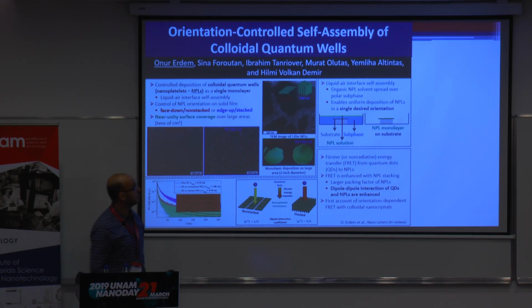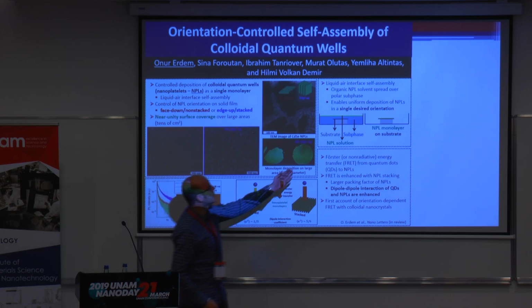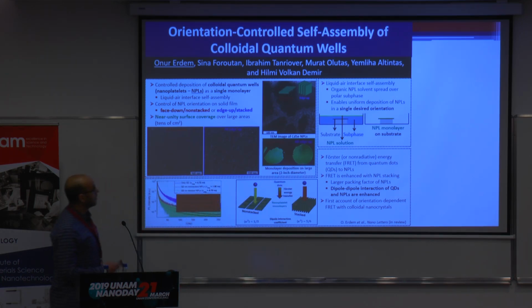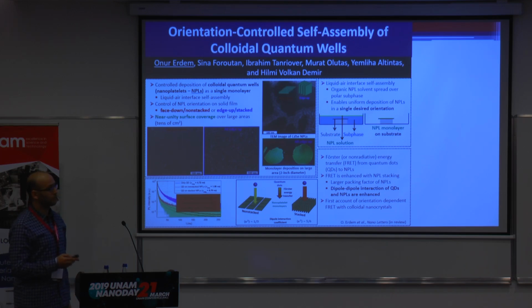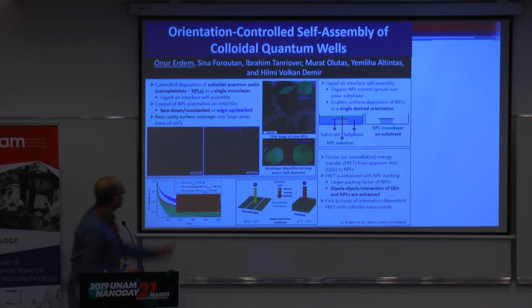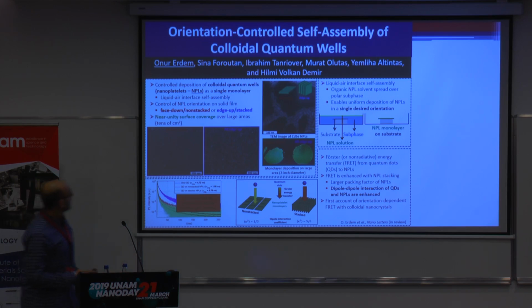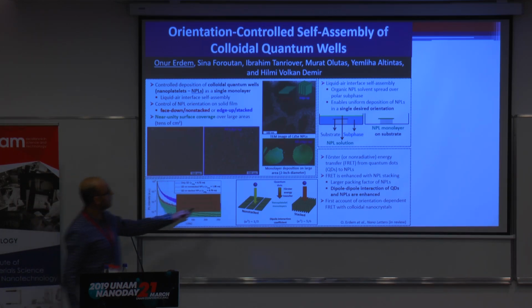To achieve this, we use what's called the liquid-air interface self-assembly technique. And thanks to this technique, we are able to control the orientation of these nanoplatelets indeed. So in these SEM images, in the image on the left, the nanoplatelets are all parallel, whereas the image to the right shows that the nanoplatelets are all in vertical orientation.